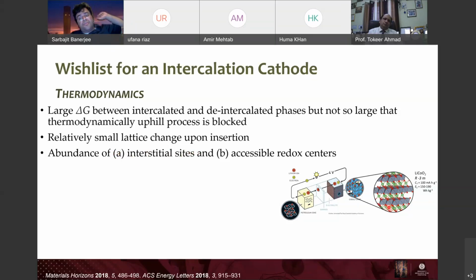And this is a key difference from a supercapacitor, right? In a supercapacitor, most or all of the energy storage is happening at the surfaces, but in a battery, you actually have redox processes going on inside the bulk of the material, right? It's happening inside the bulk because the ions are able to penetrate. And by doing so, they're accessing these transition metal sites and doing reduction or oxidation, depending on whether you're discharging or charging the battery. You're actually accessing the interior of the particle. This is, again, a very key difference from a supercapacitor, where every reaction is happening on a surface. You work really hard to increase the surfaces. But here, you're able to utilize transition metals located inside.